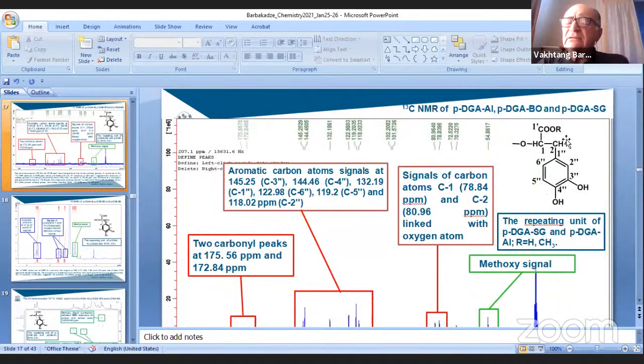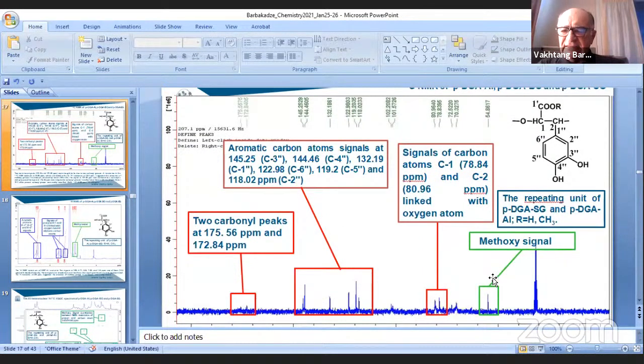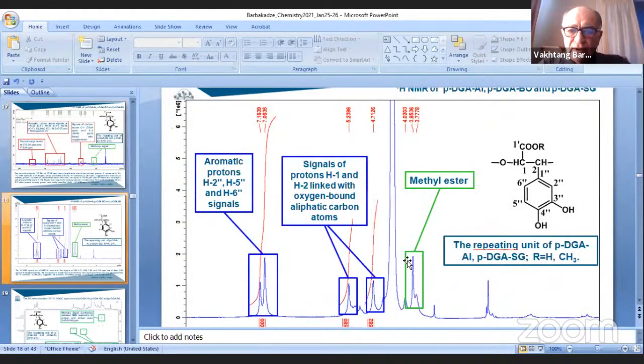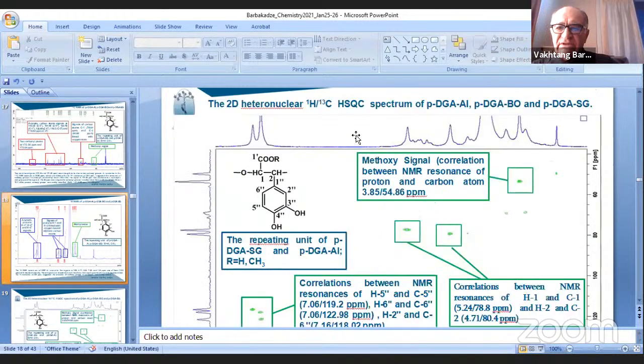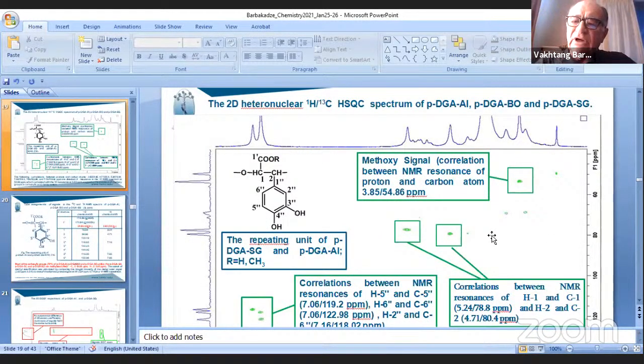had a methylated form of carboxylic groups. This signal in C13 NMR is the methoxyl signal. And in H1 NMR, the methyl ester signal is a signal with chemical shift 3.8 ppm. And this is the two-dimensional heteronuclear HSQC spectrum, and this cross peak is the signal of the methoxyl group, the correlation between hydrogen and carbon atom.